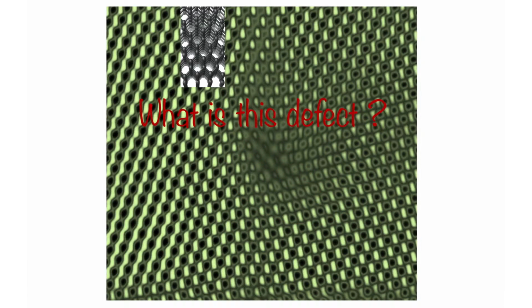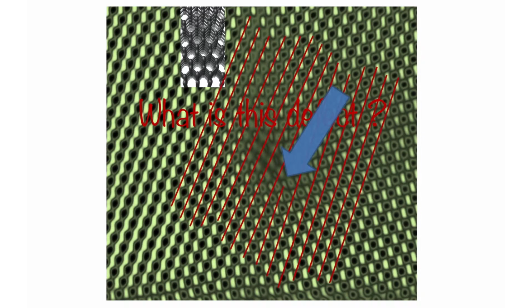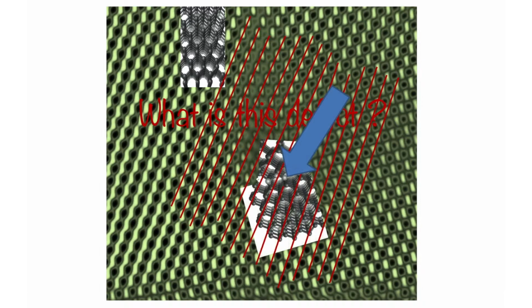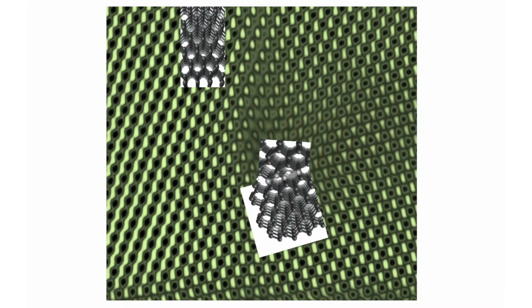It's a defect. Now what is this defect? Now if we join up the atomic rows, as I've done here, then we can see one of them is stopping in the middle of the crystal. And these atomic rows, in fact these lines now, signify crystal lattice planes. So one of these planes is stopping, and if we draw a line along the ledge of it, then this blue line here signifies a dislocation.